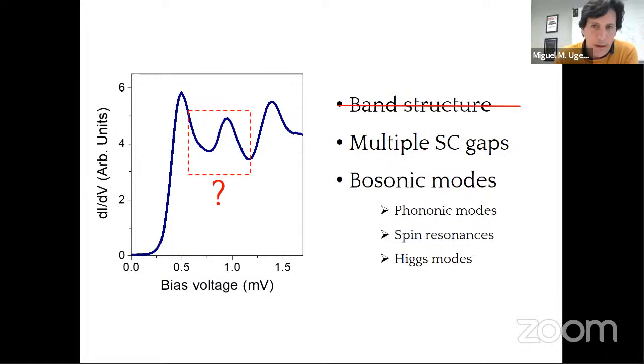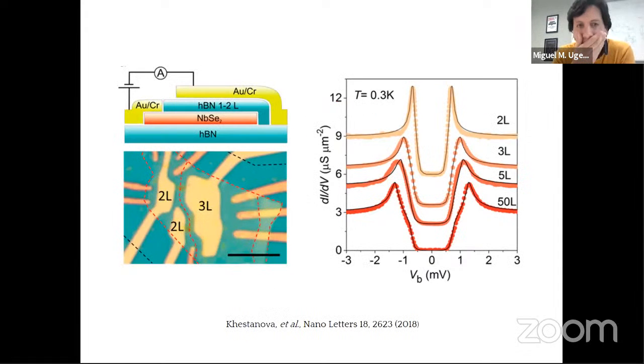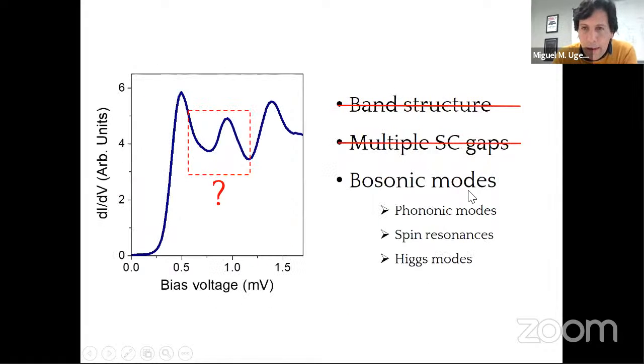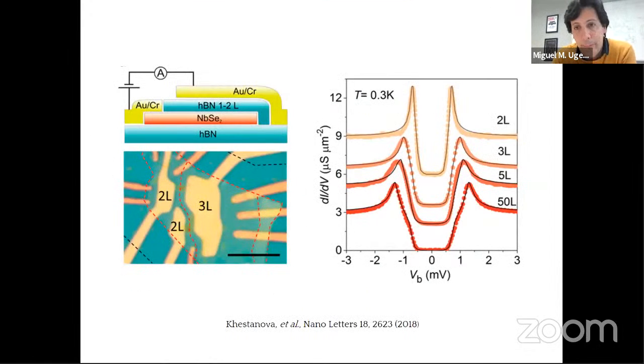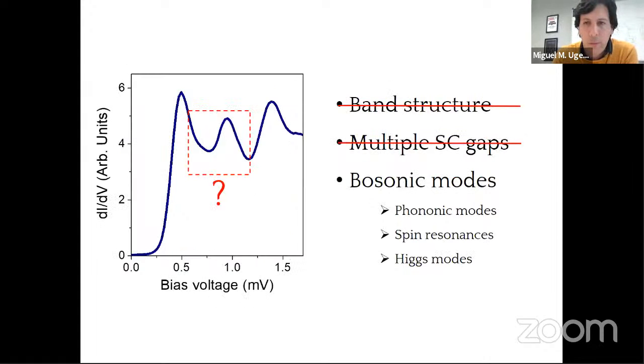Another possibility could be the existence of multiple superconducting gaps in this system. But we have learned from the beautiful experiments carried out in Manchester a few years ago that the evolution of this multi-band superconductivity in niobium diselenide is general. In these experiments they didn't reach the monolayer, but in any case, for two layers, it seems quite clear that the density of states in the two-dimensional limit only shows one superconducting gap. So we can probably rule out the existence of multiple superconducting gaps.